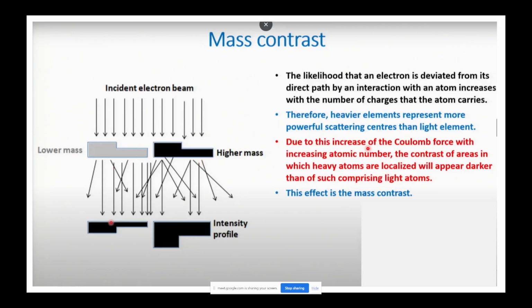Now, due to this increase of the Coulomb force with increasing atomic number, the contrast of areas in which heavy atoms are localized will appear darker than areas comprising light atoms. Here are your heavy atoms, so they will appear darker. This effect is known as mass contrast.